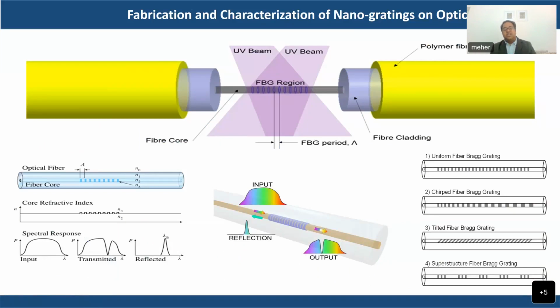And then people tried, let me give you some overview, gratings on the core of the optical fiber. You can see here very nicely that this is the core, this is the cladding, and this is the polymer coating, and this is very thin. Single mode optical fiber is around 8 microns, and multi mode optical fiber is around 56 microns. So people did it smartly. They used a UV beam to create grating patterns in the core, and they used these patterns to sense materials, gases, liquids, or changes in the refractive index, so to say.